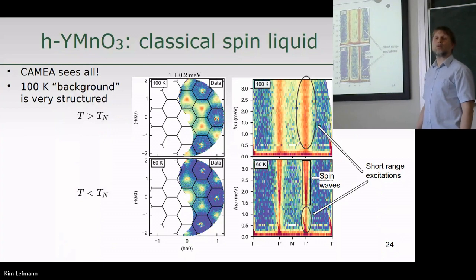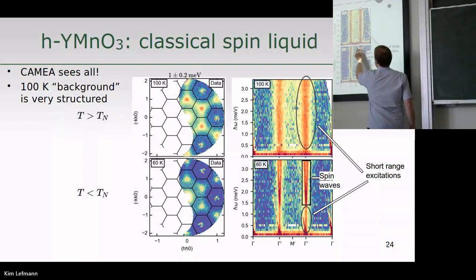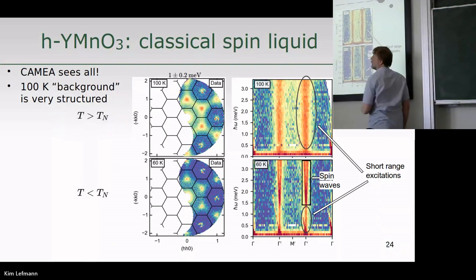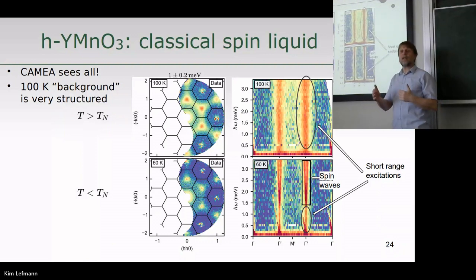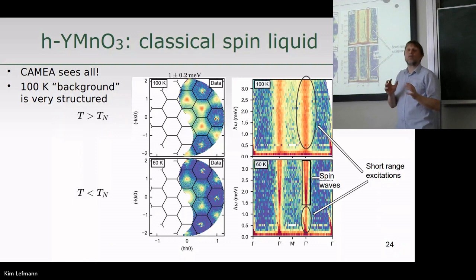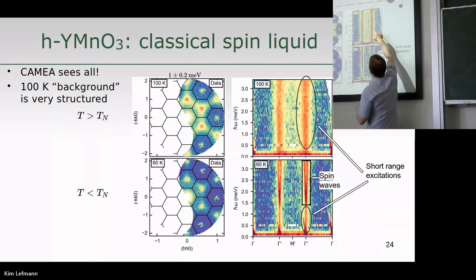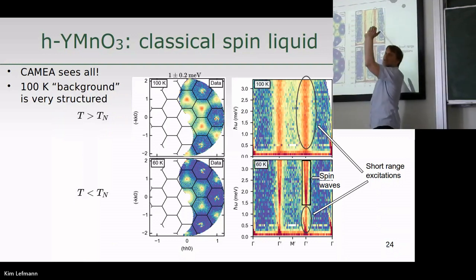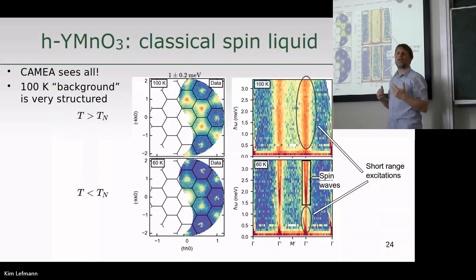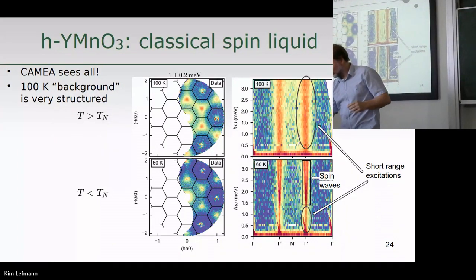Okay. That would be correlated fluctuation. They are correlated, and they have the antiferromagnetic periodicity. If you convert this into a correlation length, it's of the order of 5 to 10 lattice scales. So it's little clusters that fluctuate at all time scales, but keep their relative orientation. But I can also hint that if you get above 5 millielectronvolts, we measured this later, then they actually turn into the normal dispersion relation. So there is a crossover. It's a very strange thing. It's also rather disordered because the temperature is high. So this is some strange thing too.